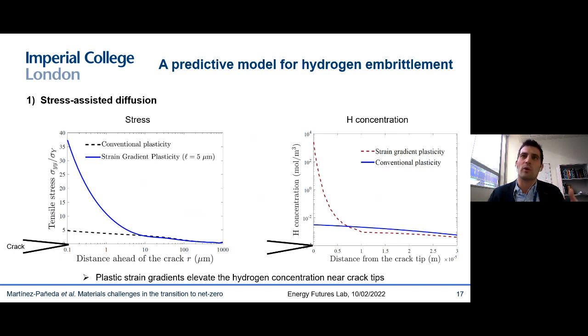So these are the distances where conventional material models, like von Mises plasticity, break down. So you really need to enrich your constitutive description of your material to capture the mechanisms that are governing material behavior at those scales, which has to do with GNDs and plastic strain gradients. So we have done that. We have used these more enriched strain gradient plasticity models that better describe what is happening ahead of cracks at those shorter distances. And what you see here, I'm plotting the stresses ahead of the crack. You can see that as you approach the crack, the stresses that you predict are much larger than those that you get with conventional models. And the same goes, of course, for the hydrogen concentration. You can see that you get much higher hydrogen content. So you really need to get these two right if you want to have a predictive model.